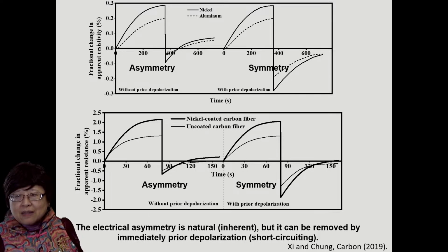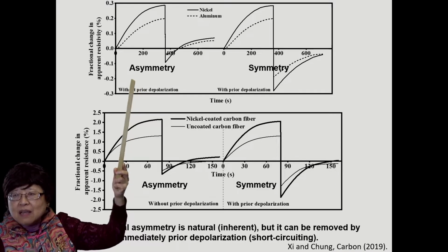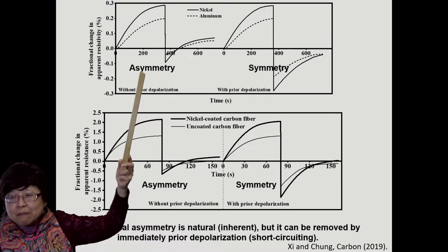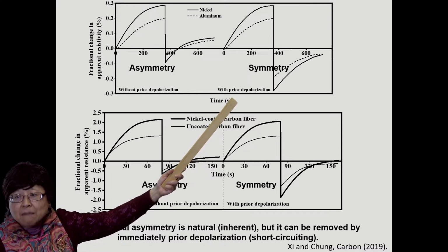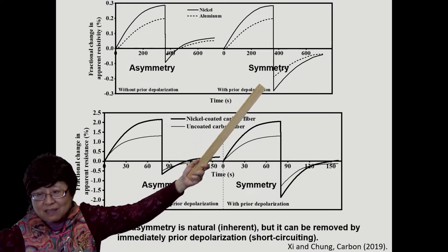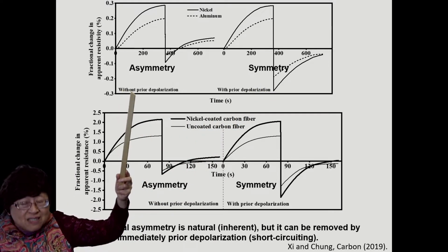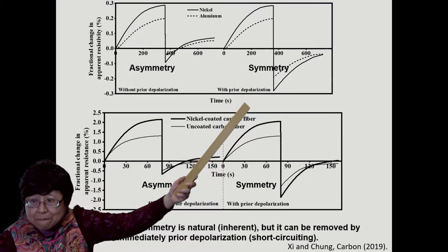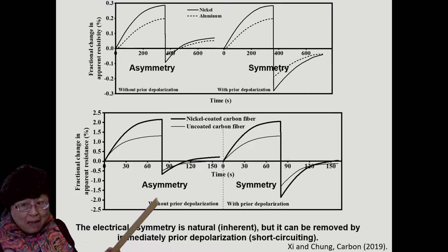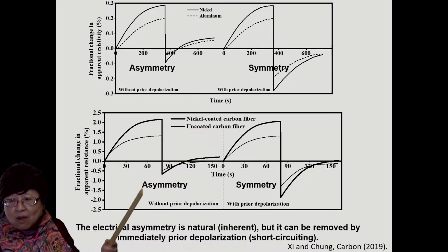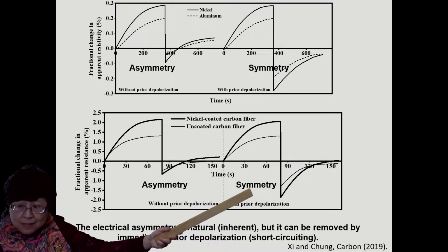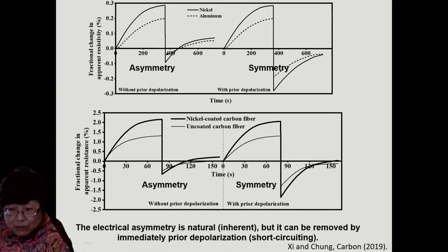Now, I mentioned the asymmetry, and this is a similar asymmetry as noted for nickel and aluminum, two other metals. However, if one short circuits the two electrodes immediately before the testing, and short circuits it for 6 minutes, one forces it to be symmetric. That is, the electrical asymmetry is naturally there. To kill that asymmetry, you have to depolarize it right before the testing. Similarly, it happens for carbon fibers. Shown here are uncoated and nickel-coated carbon fibers. Again, naturally, it's asymmetrical, but if you depolarize it right before testing, then it becomes kind of symmetrical.